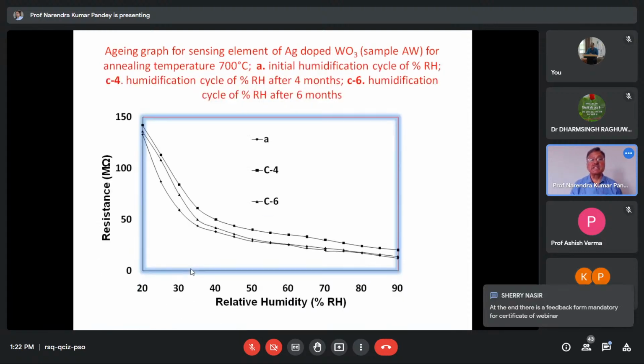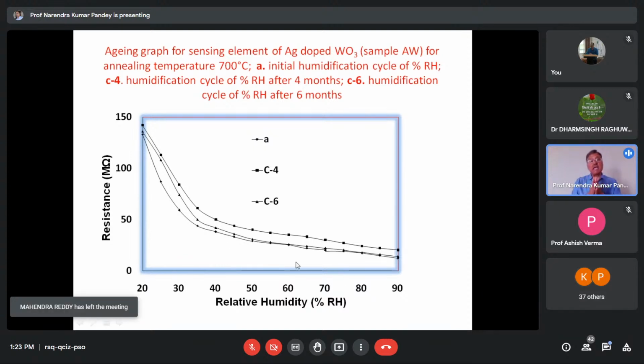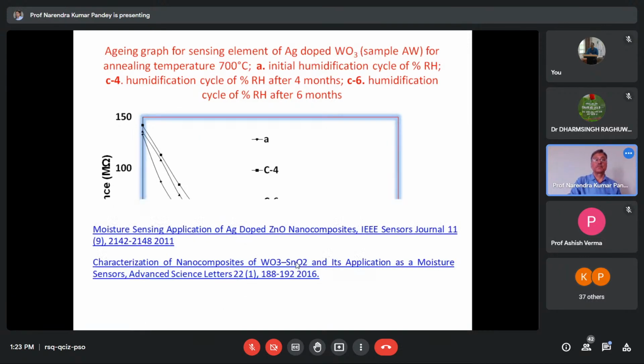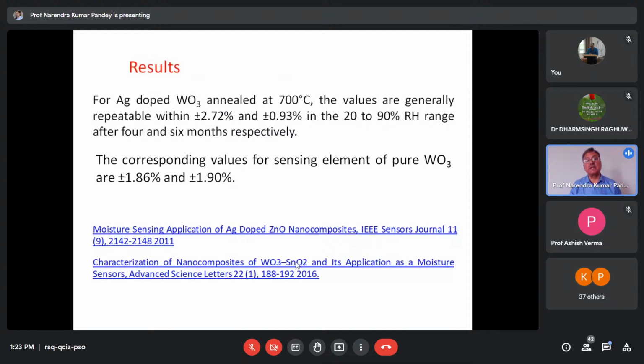Now, the aging graph for the sensing element: you can see A for the increasing cycle, C4 after 4 months, and C6 after 6 months. You can see that the aging has been reduced and the graphs are following almost the same trend. Results: Ag doped WO3 annealed at 700 degrees centigrade. The values are generally repeatable within ±2.72% and ±0.93% for Ag doped WO3 in the 20 to 90% RH range. The corresponding values for the sensing element of pure WO3 are ±1.86% and ±1.90%. So these are very acceptable results, with your error or aging within plus or minus 2 to 3%.